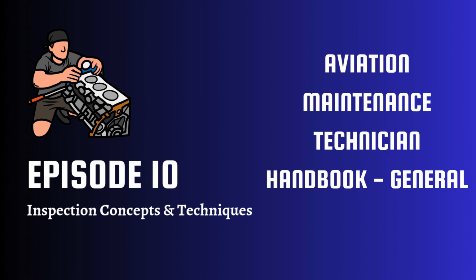What's the usual procedure? For any parts that were actually submerged, it generally requires complete disassembly of those components, rigorous cleaning, thorough drying, often using special ovens or desiccants, and then application of corrosion-inhibiting compounds before reassembly. What about non-metallic parts? Carpet, seats, insulation? Many non-metallic parts, especially avionics, instruments, upholstery, and insulation, often require outright replacement after significant water immersion. Water gets trapped, promotes mold, and can cause irreparable damage, especially to electronics. It's a huge, expensive job to recover a flooded aircraft properly.